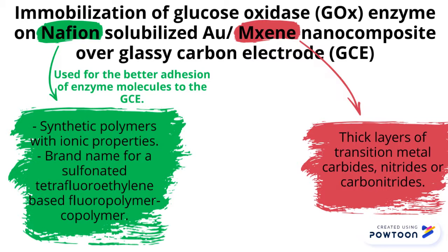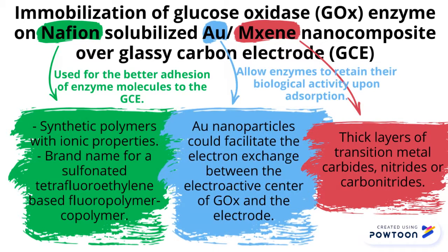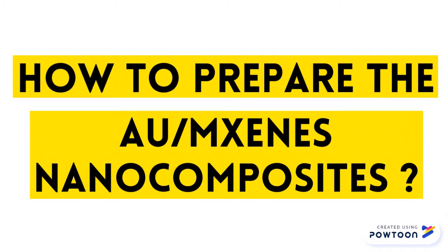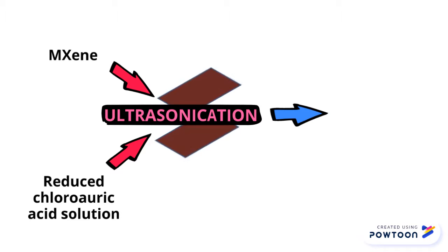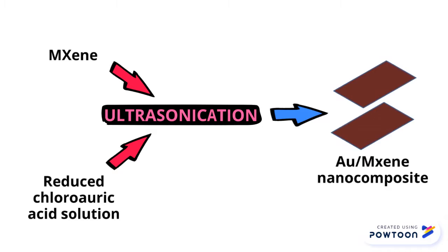As for Au nanoparticles, also known as gold nanoparticles, they facilitate better electron exchange between the electroactive center of GOX and the electrodes. Au nanostructures allow enzymes to retain their biological activity upon adsorption. To prepare the Au-MXene nanocomposites, the titanium carbide nanosheets (MXene) are mixed with chloroauric acid solution. The resultant mixture is then subjected to ultrasonication. The Au-MXene nanocomposites are then sonicated in Nafion solution, and the suspension is film-cast onto the surface of the glassy carbon electrode and allowed to dry slowly.